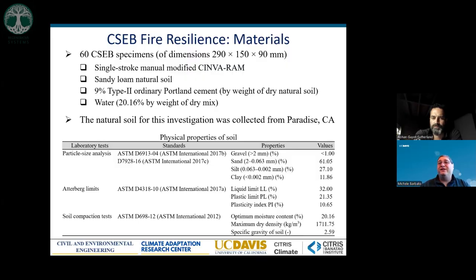Here are the details on the material. We used a 9% Portland cement amount in weight of dry natural soil. And we did the investigation of all of the physical properties of the soil in terms of particle analysis, Atterberg limits, that are fundamentally the amount of water where the soil starts changing physical composition. We did the soil compaction test to find the optimum moisture content that would be needed to produce the maximum compaction of the material that is optimal for our blocks.